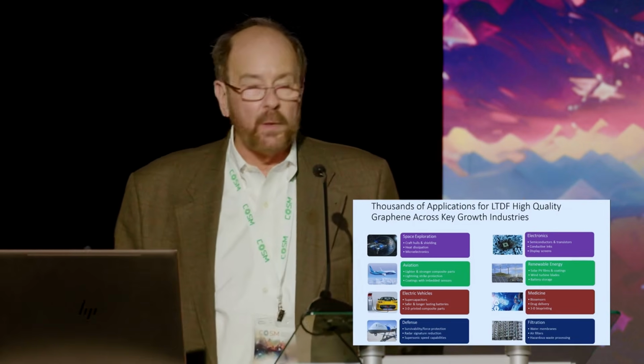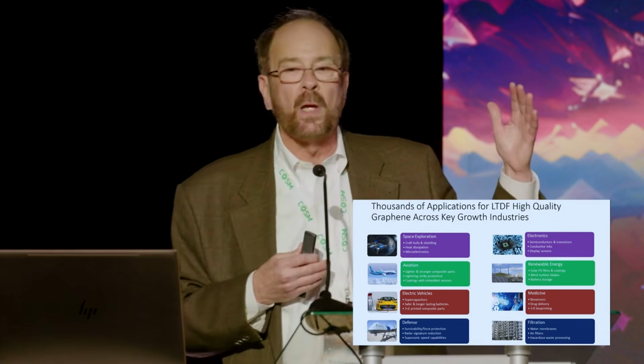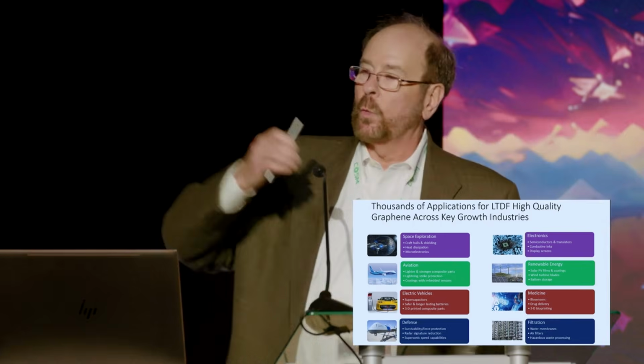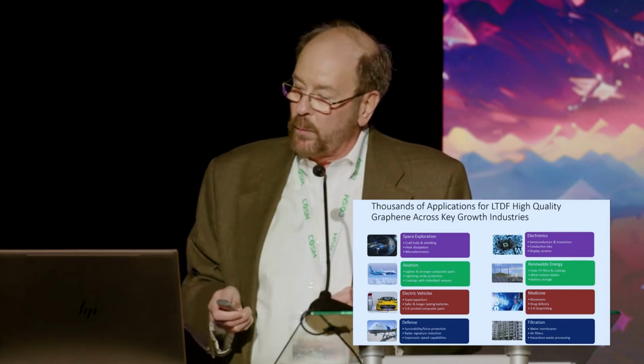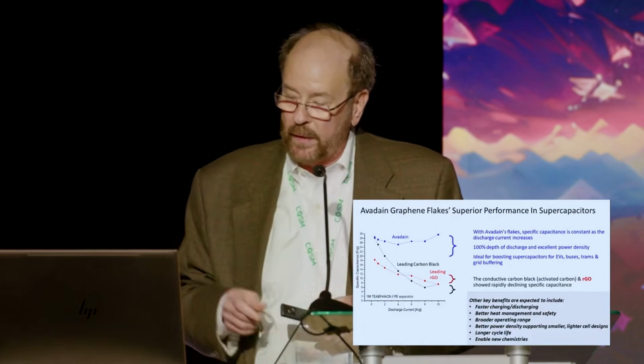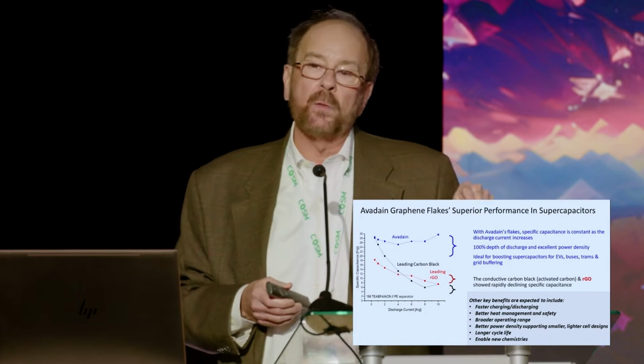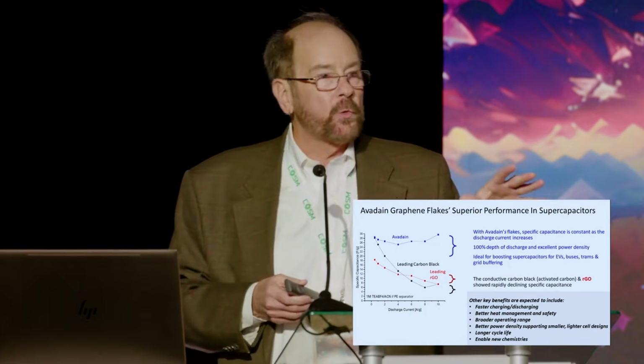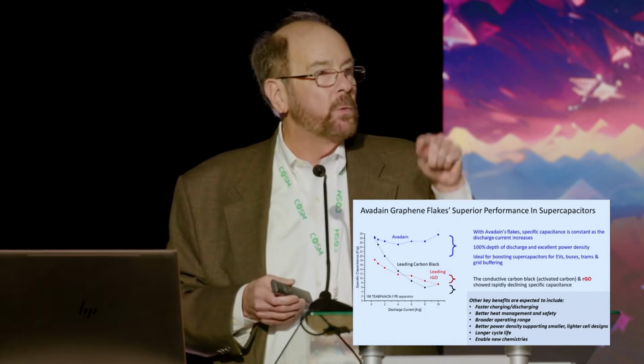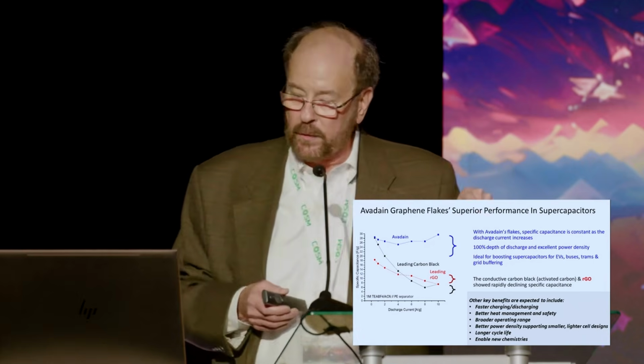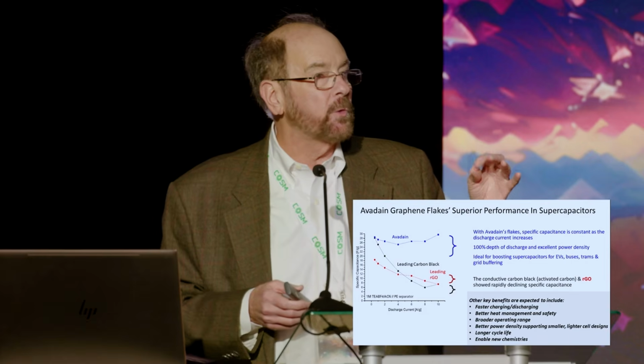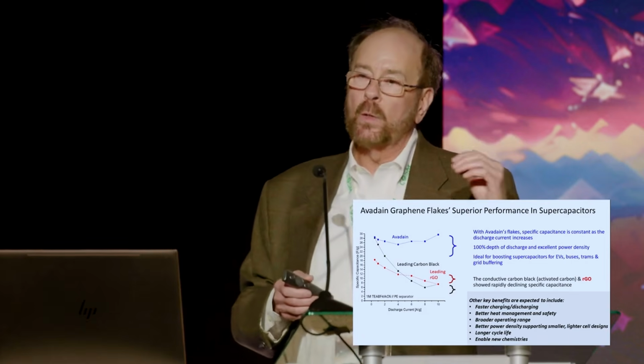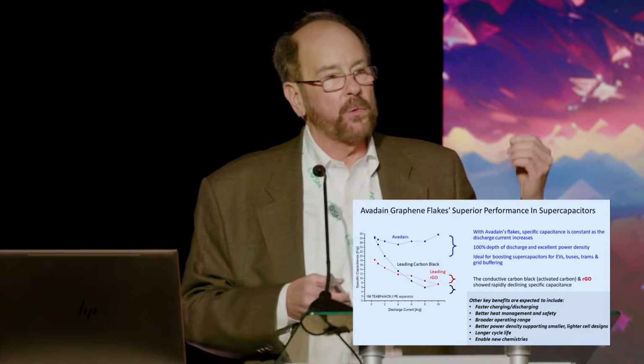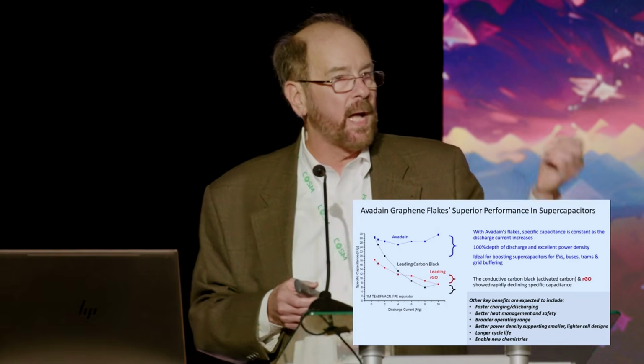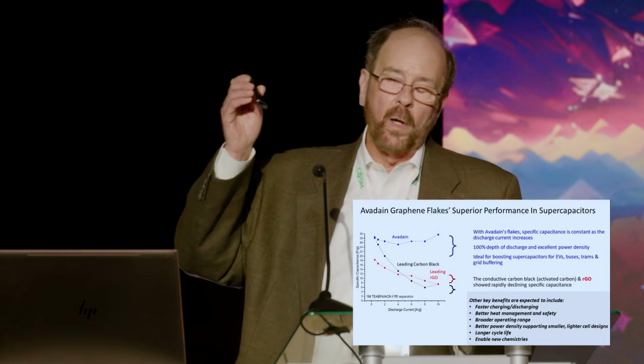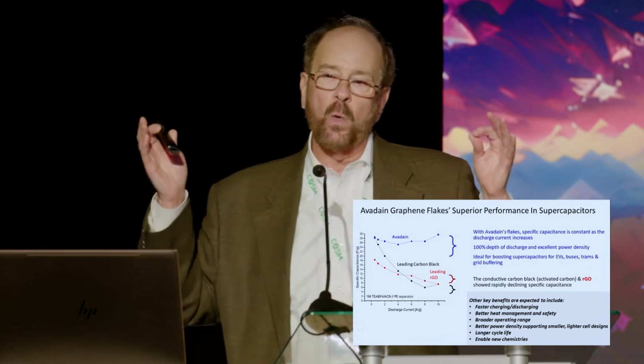And in renewable energy, graphene can be used for everything from long-haul transmission lines to connect new and renewable energy sources to consumers. One of the areas where we've done a little bit of work is in supercapacitors. And here, this is very interesting because graphene can be used as the electrode material in supercapacitors. An industrial supercapacitor might cost $1,000 to $3,000, but using $6 worth of large, thin, and defect-free graphene flakes can have these results. First, the specific capacitance remains the same as the discharge current increases. So as you use the supercapacitor to rapidly charge, we see that with the current materials, reduced graphene oxide and carbon black, the specific capacitance decreases, whereas the specific capacitance of high-quality graphene remains the same.